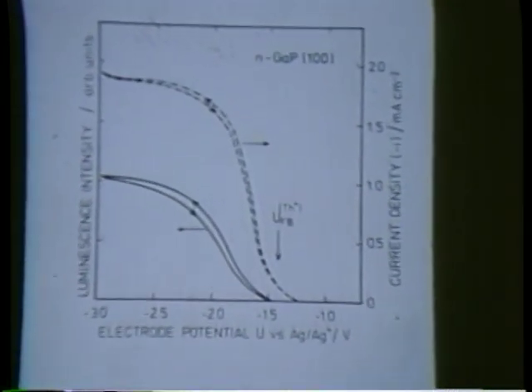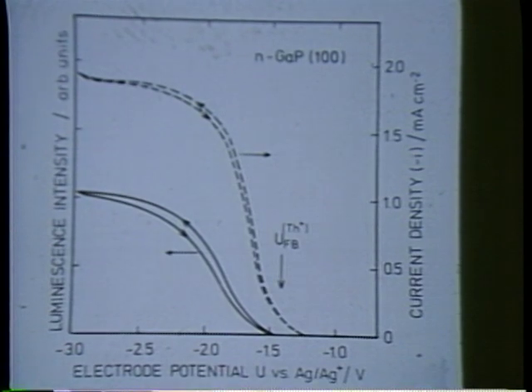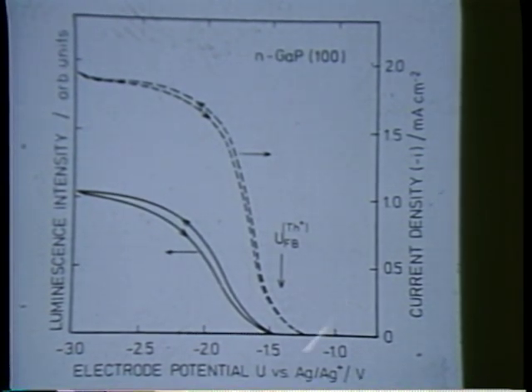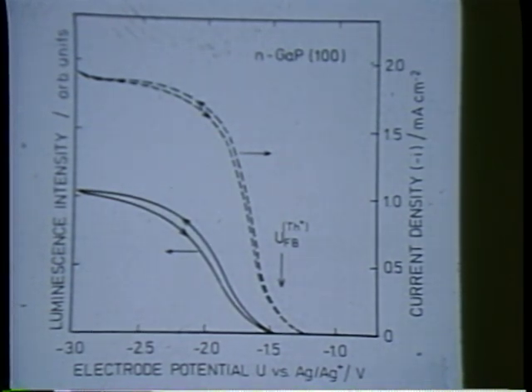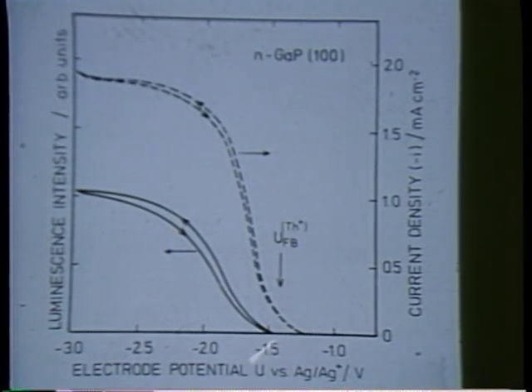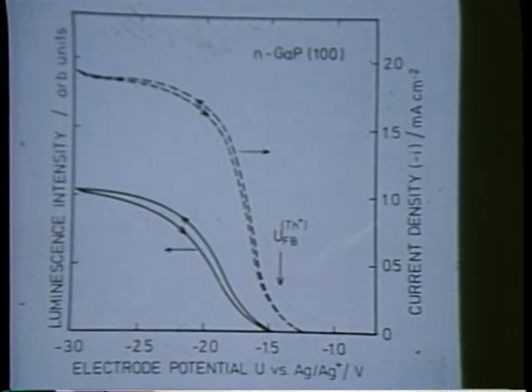In the non-aqueous solution, we had to use non-aqueous solvents in order to have enough polarizability and stability of the system. And you see, we have this negative bias. That means if we decrease the band bending and increase the concentration of electrons on the surface, a current starts, and we see a current because of an electronic current. We don't know what the mechanism is. It could be direct reduction, it could be a conversion to injected holes.